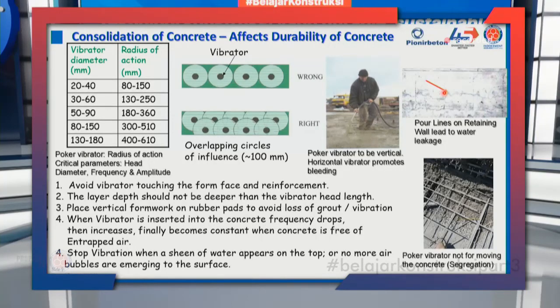You get a pour line. The pour line is a defect. Water can enter. And if it happens to be a retaining wall, water will start gushing through here. So ensure that your length of vibrator at least matches the depth of your concrete layer. The third thing, people use vibrator to move the concrete. Vibrator is not meant to move the concrete.